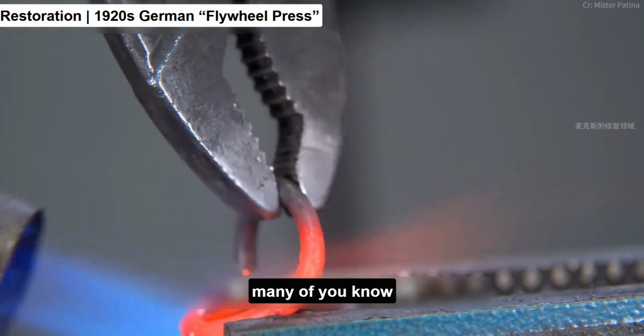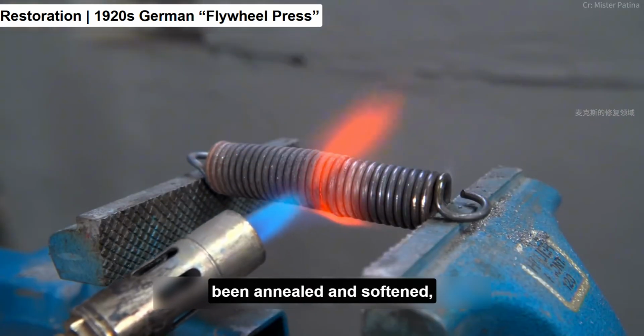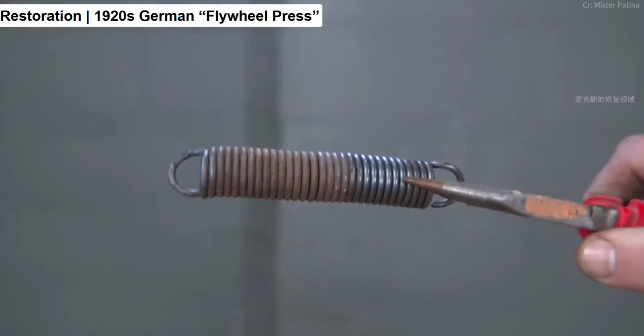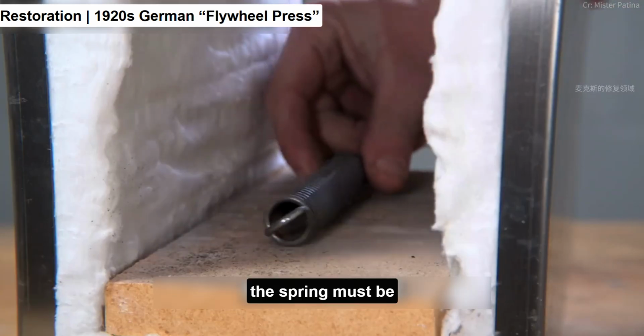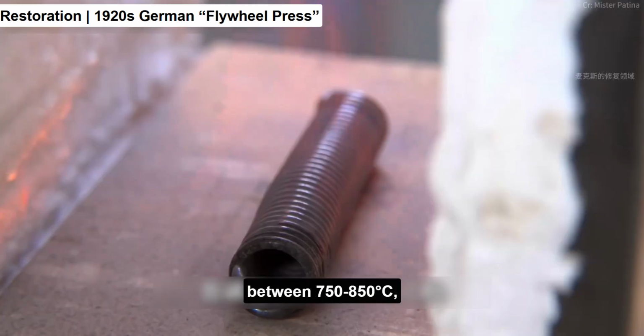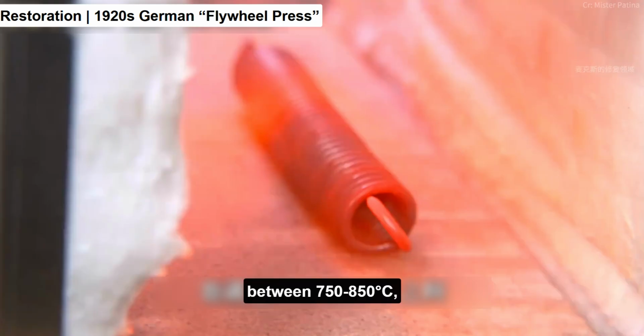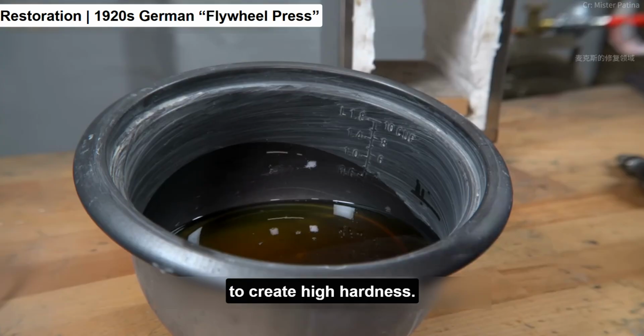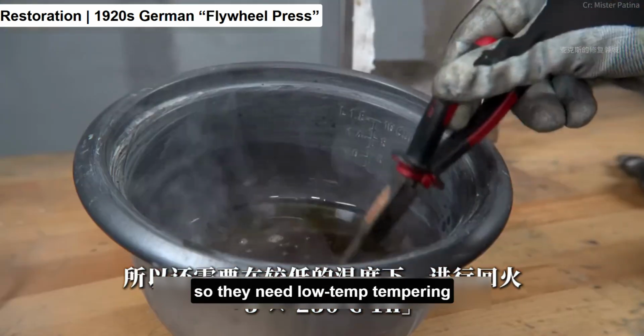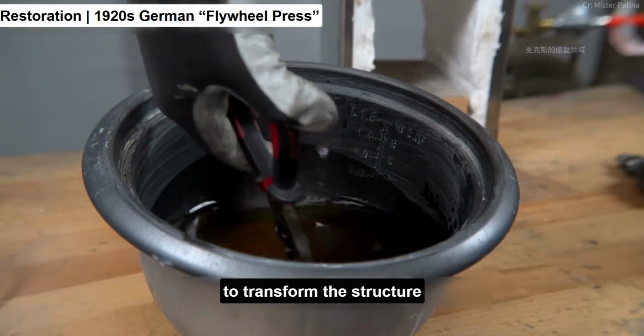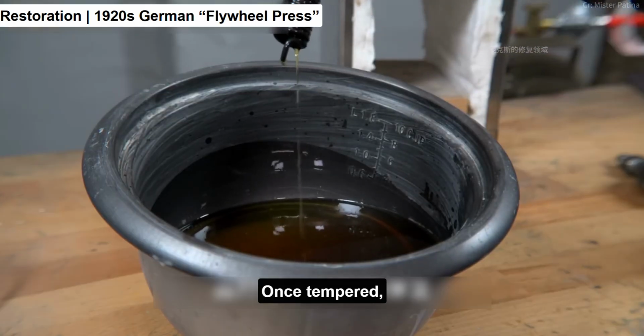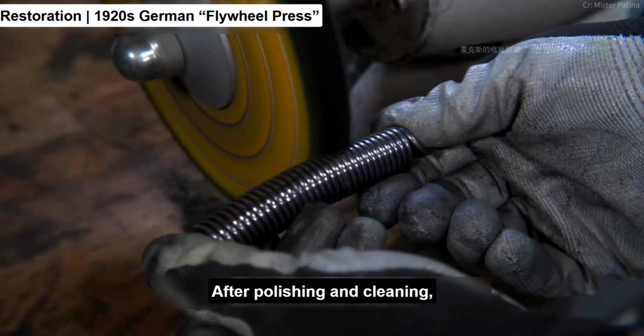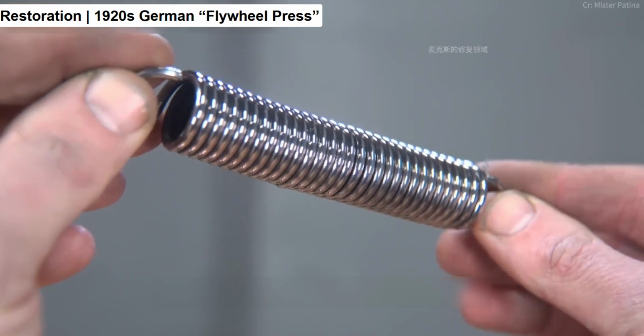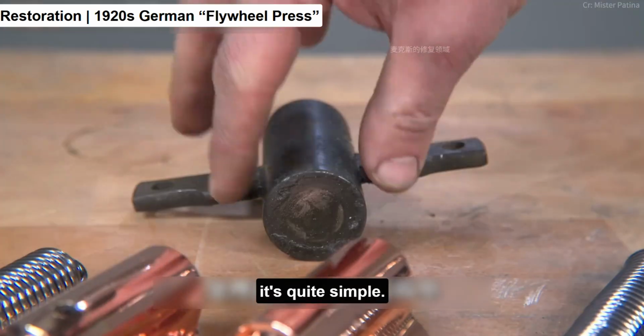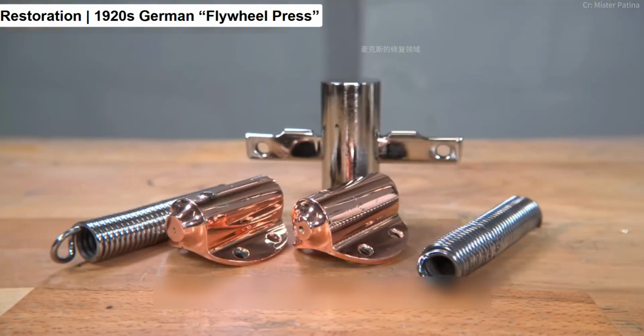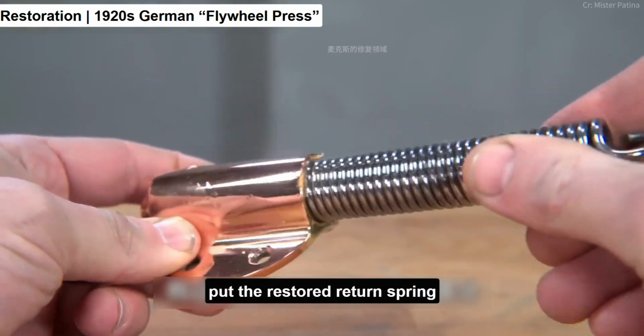Now, I am sure many of you know that after heating, the spring has been annealed and softened, losing its elasticity. To restore elasticity after straightening, the spring must be heated to the austenite zone between 750 to 850 degrees Celsius, then oil quenched to create high hardness. But quenched springs are brittle, so they need low temperature tempering to transform the structure and balance strength and toughness. Once tempered, the spring regains its elasticity. After polishing and cleaning, these two springs are done. As for the cross-shaped part, it's quite simple. Just reshape and nickel plate it. Now Pargo can put the restored return spring back into place.